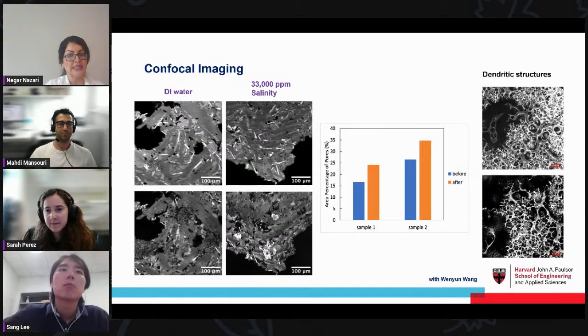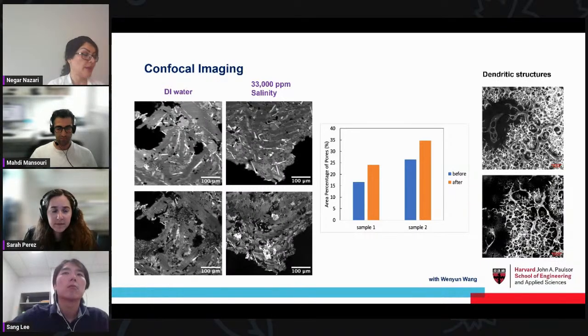So we think that those can be some indication of the hydrothermal reaction that happened on the surface. I do not have any explanation for that. It's just interesting. I never ran into it anywhere. So we are still working on understanding that. But in 2 weeks, when we went back to the same samples and looked at them, we observed that those dendritic structures are gone and we don't see them on the surface anymore.